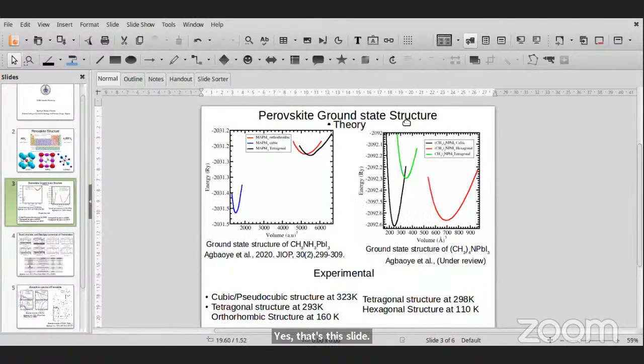So here we are looking at the energy with respect to the volume, and the volume is far apart in the first graph because the cubic structure is smaller than the orthorhombic and the tetragonal structure. The cubic has the same value in XYZ, which is about 5 point something Angstrom, while that of the orthorhombic and tetragonal is quite larger. We are looking at the unit cell of both materials, and obviously orthorhombic is larger than cubic, and also tetragonal is larger than cubic. So that is why we have them far apart.